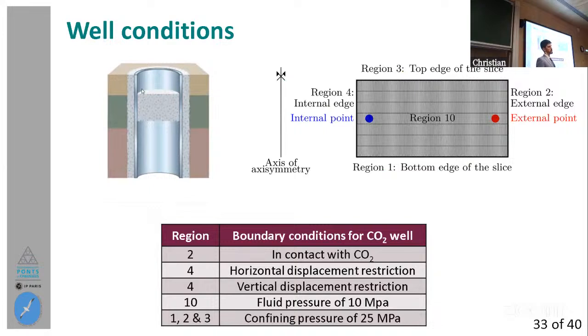So now I will model the well conditions. Here I present you, as I have presented before, the general geometry I have used, in which I have changed it a bit. I have again a rectangle, because it's easy, and then in the middle an axis of symmetry, located in the middle of the well. Then we have region 4, which is the internal edge of this slice of cement annulus, in contact with the casing of the well. Then we have region 2, which is in contact with the formation rock. And then we have regions 3 and 1, which are in contact with the other slices of cement.